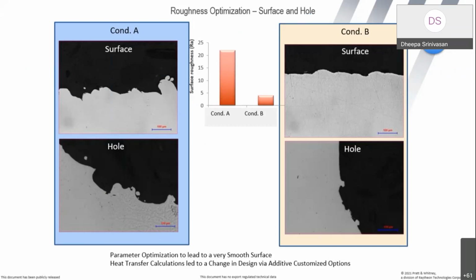And how we overcame this particular challenge is to partner with our CFD colleagues. When you have surface roughness in an internal cooling hole, with this kind of morphology that you're seeing out here with very, very sharp corners, this can act as a KT factor or stress concentration factor and cause premature failure. That is number one. The second challenge is that the circle with roughness will have a more constricted volume compared to one without. That means the amount of fluid that can flow through will be reduced, not to mention the stress concentration factor of something as sharp as this.